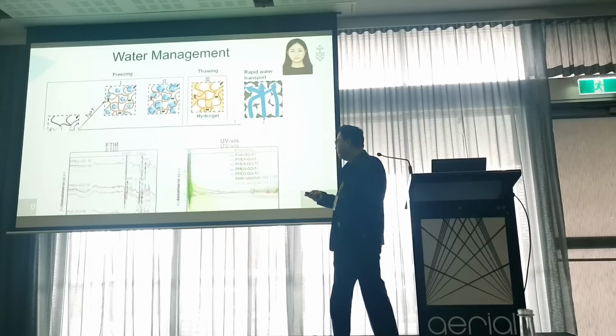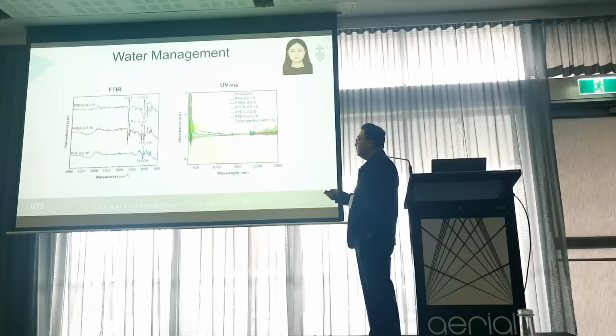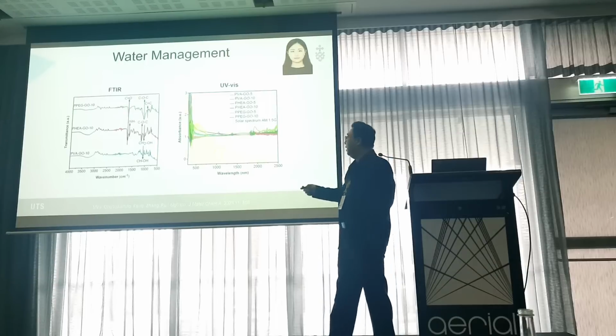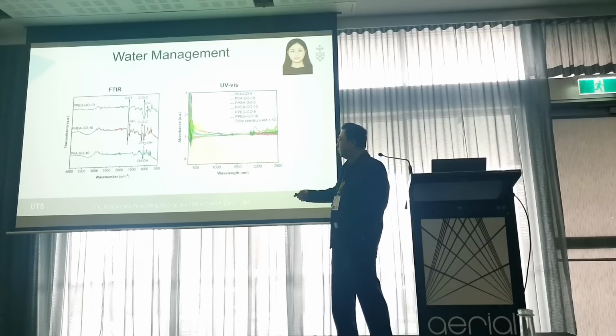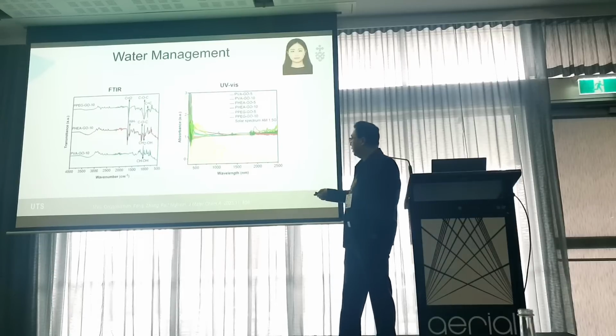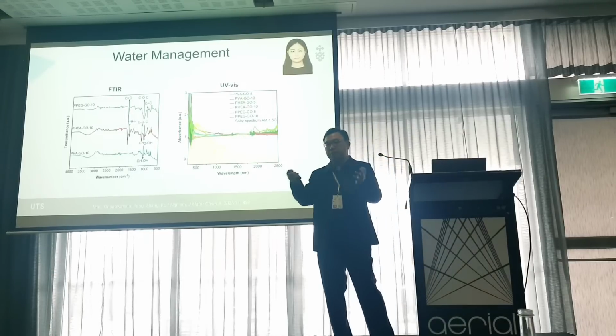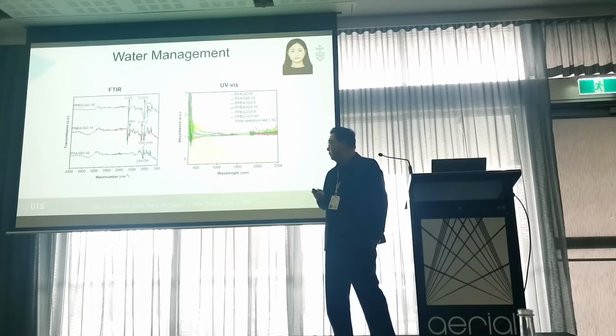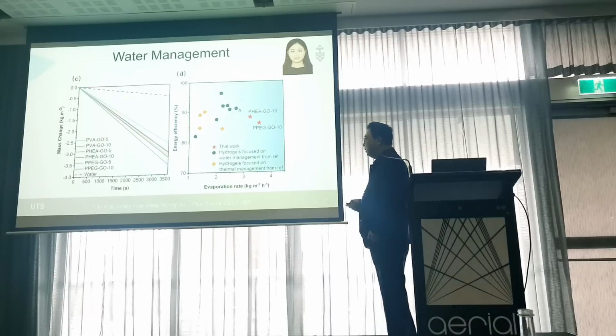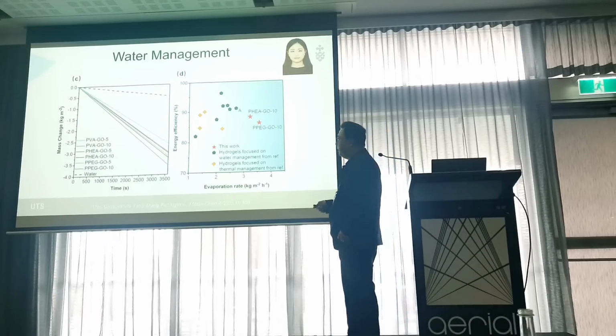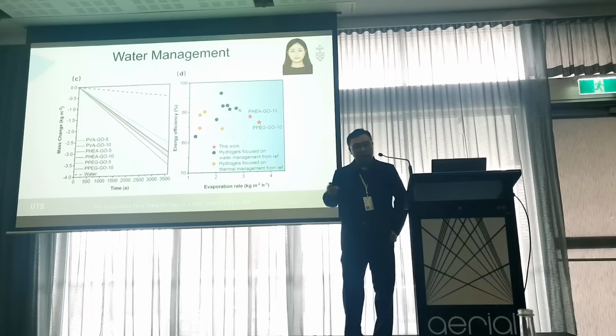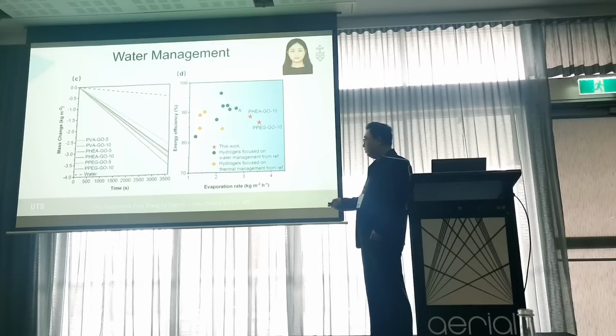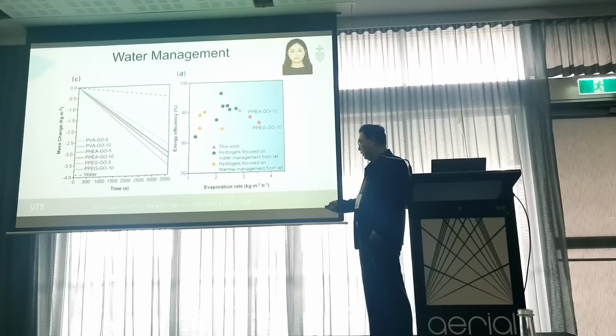Yeah. So we definitely characterize these hydrogels, FTIR or UV-vis. You can see all the characteristics of the different hydrogels were observed. And all the hydrogels show a broad solar absorption spectrum. So then we test the water evaporation performance of all these hydrogels. As expected, the PEG hydrogels with graphene oxide as the photothermal materials show the highest water evaporation rate.